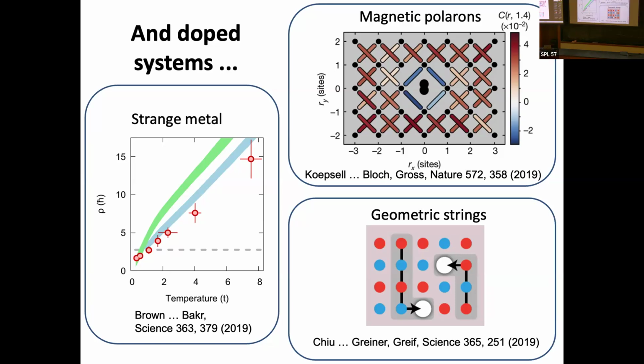Pausing for the folks on Zoom. Maybe I missed something, but are you saying that you're measuring resistivity? So in this experiment, we don't measure the resistivity directly. We kind of go around it in a roundabout way. We use the Nernst-Einstein relationship. So we measure the diffusivity actually, and then we measure the compressibility and multiply them to get the conductivity, take the inverse to get the resistivity. Okay. Yes.